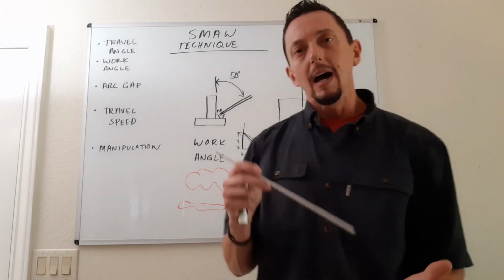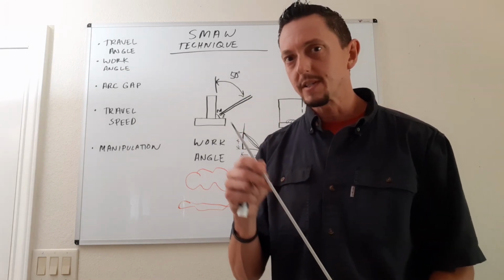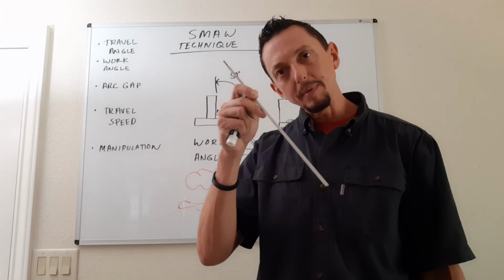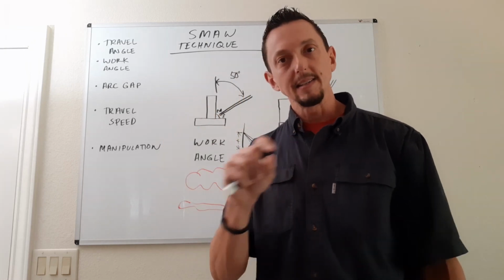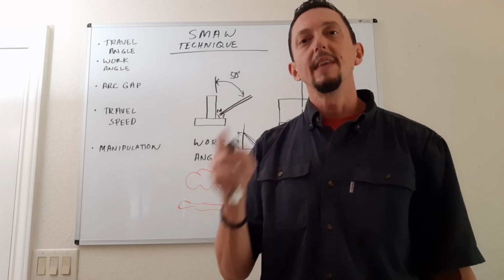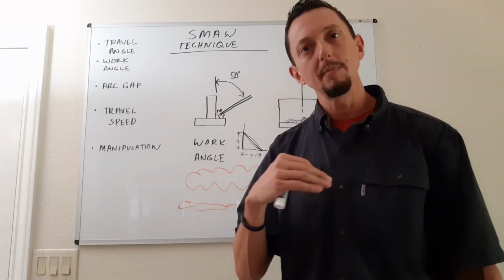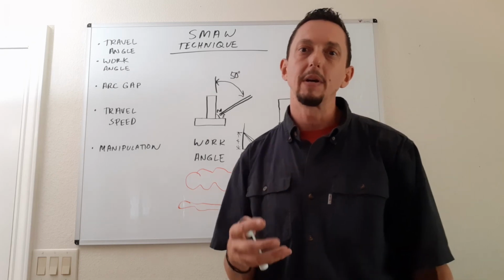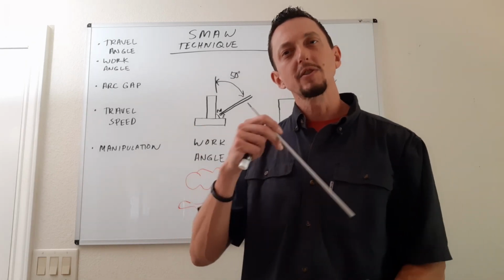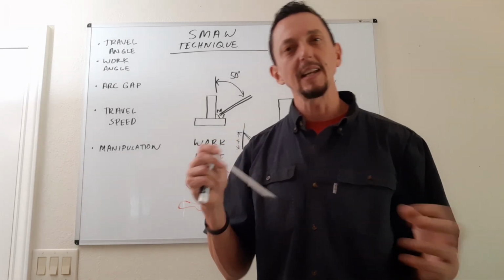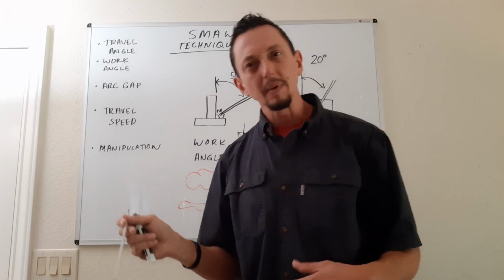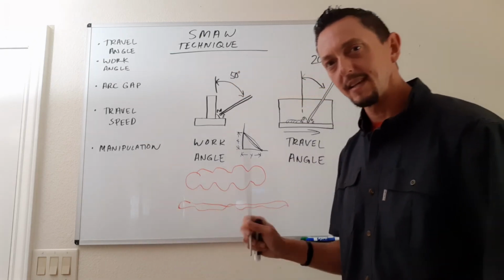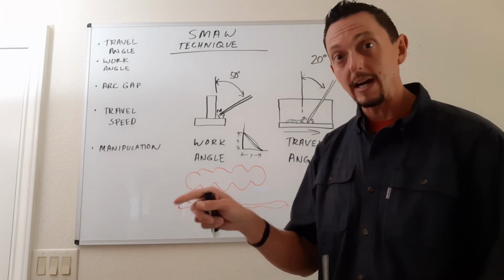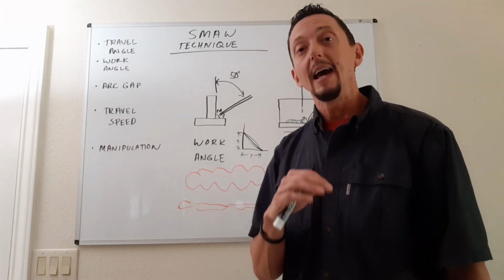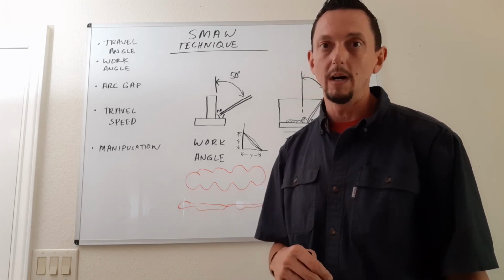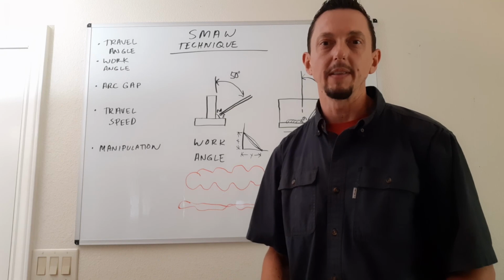Manipulation, though, I would recommend if you're welding for the first time, just try to be consistent first of all, okay? Get a consistent bead just dragging straight across, okay? Then later on you can develop manipulation that maybe gives you a better profile or a better appearance to your weld, or you just prefer it. But at first, try not to complicate it because you'll be doing different things and getting different results, and you won't really know if it's your manipulation or what it is. So just stick to these common things and try to drag straight across and see if you can get a consistent size and an acceptable appearance and profile to your weld. And then from there, you can develop some different things, okay?